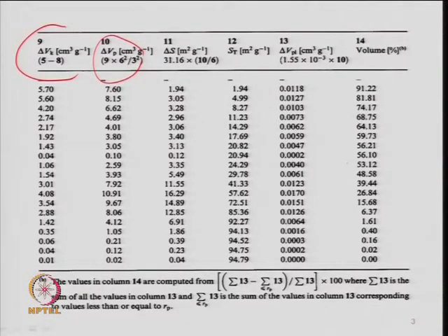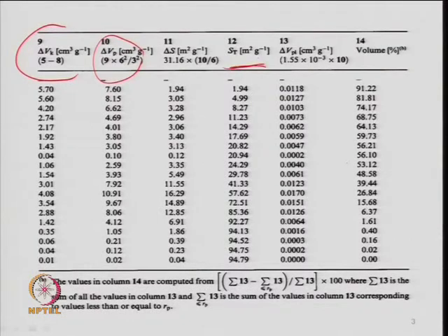You can very easily calculate that, and then you can also calculate the change in the surface area, the BET surface area, which you have calculated. Between two successive steps, what is the number of gas molecules which have desorbed from the surface, and the area of one molecule is known. So, that is the decrement or change in the surface area. I am not talking in terms of surface now, but that is equivalent to the layers, or delta t also. So, we get the total surface area, just similar to your BET surface area, but for the corresponding layer thickness.